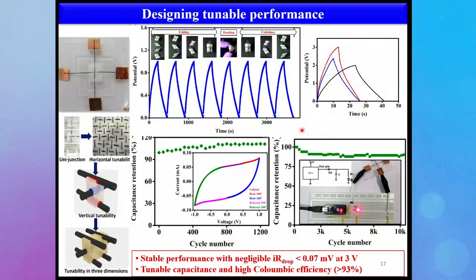How does the performance depend on thickness? Yes, Sudeep also asked the same question, about the thickness of the electrolyte sheet. Basically, if you make it too thick, then the ionic conductivity in that direction is going to get lower and lower. That means there is going to be less and less electrical double layer formation. At the same time, if you make it too thin, then you run the risk of shorting the devices. So this has to be maintained at an optimal thickness. So something around 150 microns is what we have worked out.